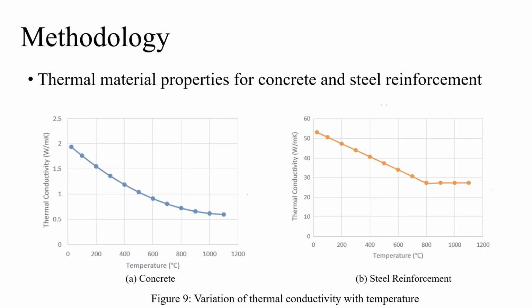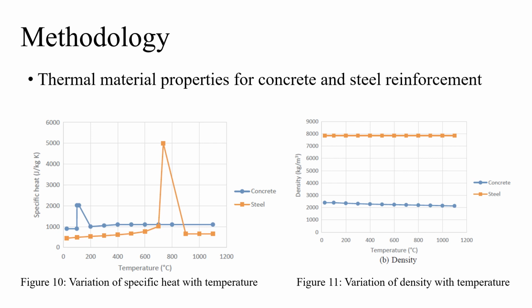The finite element model incorporates temperature-dependent material properties. These include both the thermal and mechanical properties of concrete, steel reinforcement, and CFRP. Figure 9 shows the variation of the thermal conductivity of concrete and steel reinforcement with temperature. These material models were adopted from Eurocode 2. Similarly, specific heat and density of concrete and steel reinforcement were adopted from Eurocode 2, as shown in Figure 10 and Figure 11.